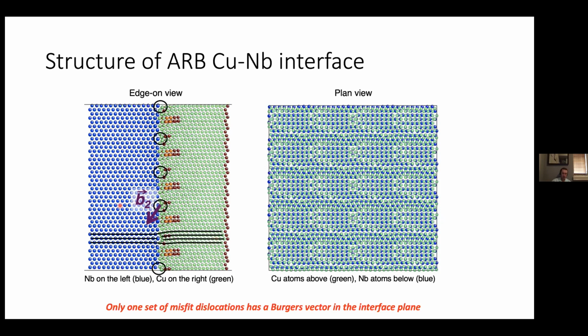You can actually figure out the Burgers vector of that dislocation. It happens to point in this direction. And looking at it, you can immediately see the Burgers vector of this dislocation has a component that points out of the interface plane. In other words, the glide plane of that particular dislocation is not going to be the interface plane.